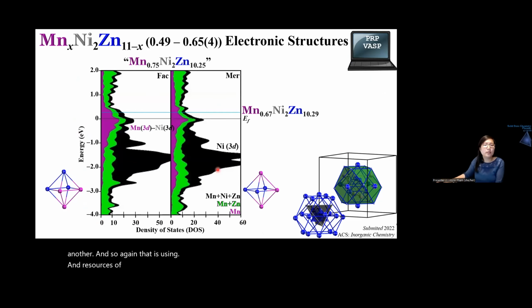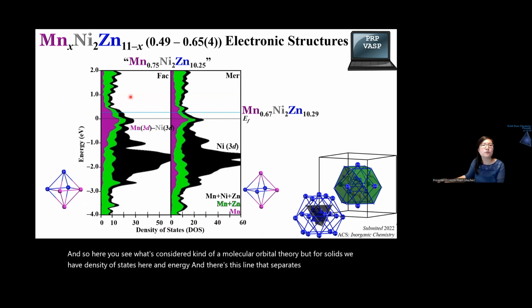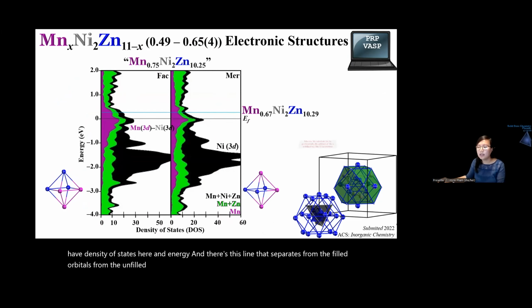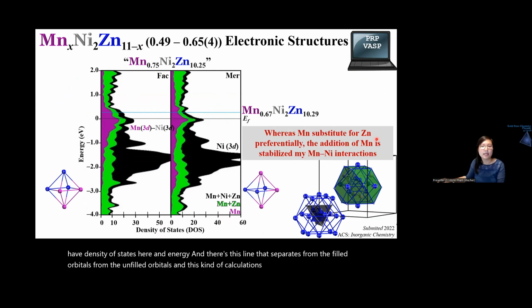And so now we can also look at how electrons in various orbitals are interacting among one another. And so again, that is using resources of PRP. And so here you see what's considered kind of like a molecular orbital theory, but for solids, we have density of states here and energy, and there's this line that separates the filled orbitals from the unfilled orbitals. And this kind of calculation then allows us to realize that manganese substitutes for zinc in the structure, but is actually stabilized by manganese 3d, nickel 3d interactions.